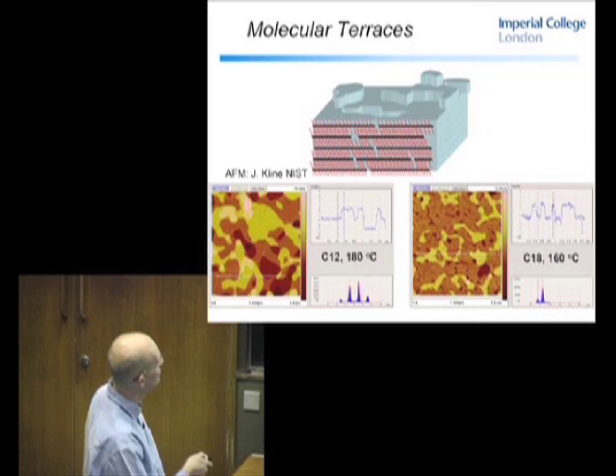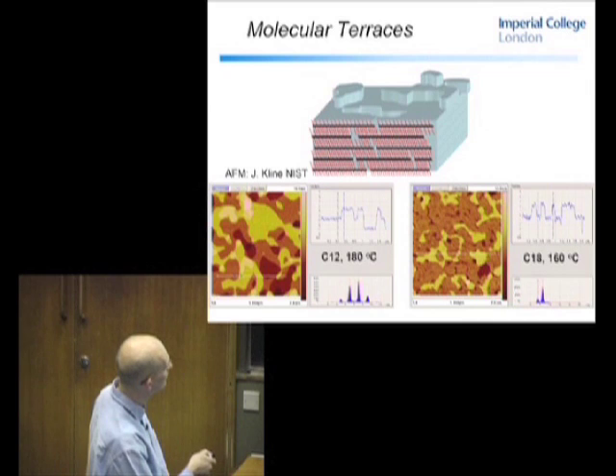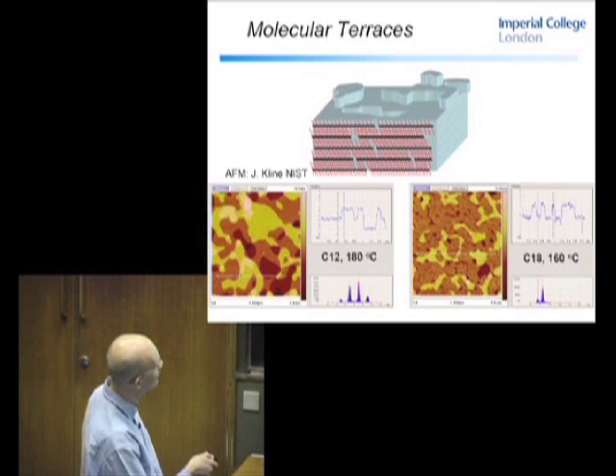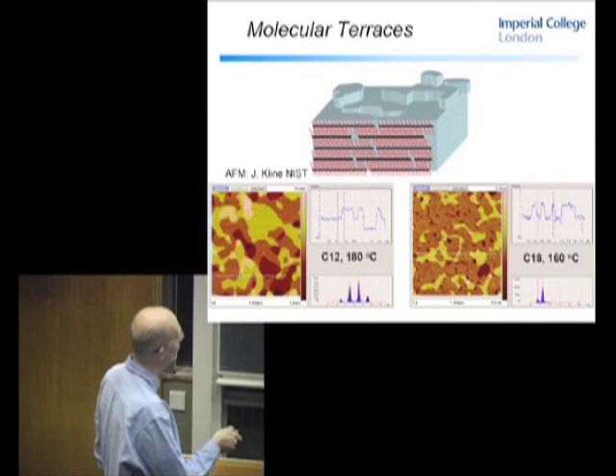Yeah, this is the terracing effect. So if you look at the topography along this line here, you see it's a dark colour going from the sort of darker brown to the yellow. Is it this region here? You see this basically steps up, goes back to the brown, so you're back down here, back to the yellow, back up, and then it goes into this even darker region, which is a two-step down height difference. And this height, this is nanometer scale, as I mentioned, is equal to the alkyl chain length at the angle at which it is projected. And you see when you move from C12 chain to C18 that this step height is larger. Not quite so well defined terraces here, so the noise is a bit more, but yeah, quite nice. And you see this is a histogram of heights.